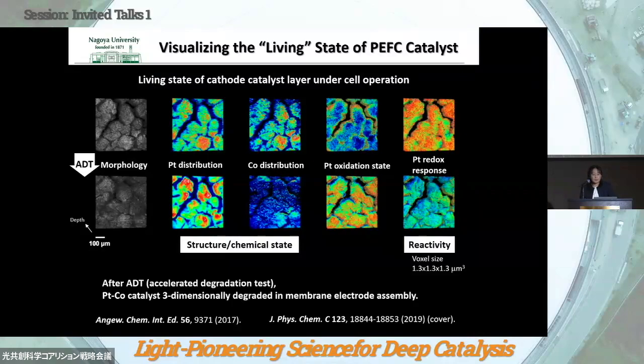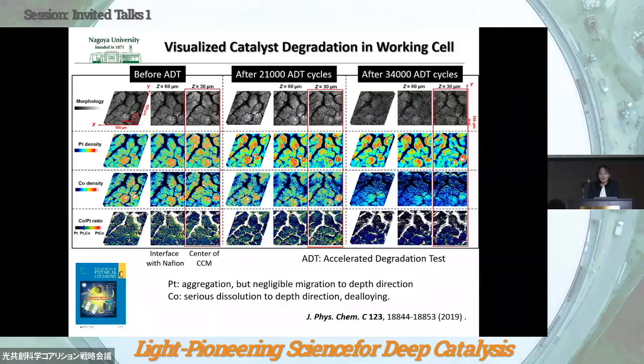So this kind of three-dimensional imaging provides us not only the structure, but also the chemical state and reactivity parameters at each part of the membrane electrode assembly under the working conditions. And by the analysis of the XAFS CT spectra, we achieved the visualization of catalyst degradation of the platinum cobalt catalyst in the working cell.